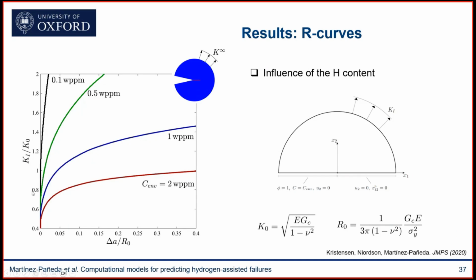So what I'm measuring here is a measure of the crack tip load, and this is the crack extension. You can see, in agreement with experimental observations, that if you increase your hydrogen content, then you get a lower fracture resistance, as you see here.